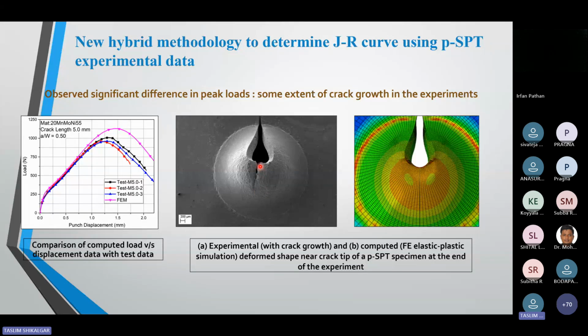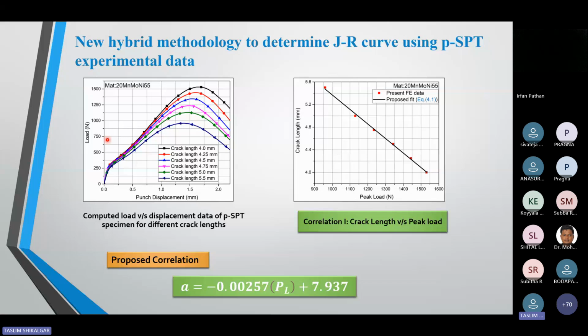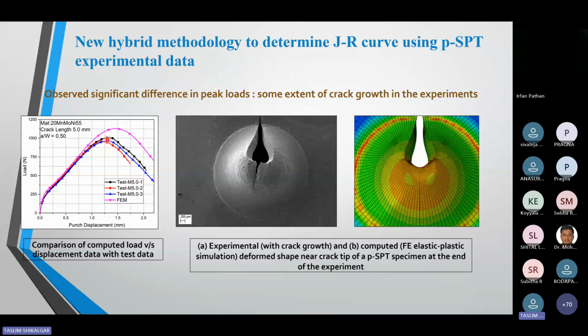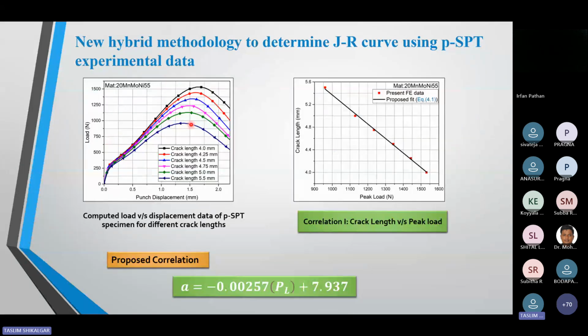So I want to find out the crack growth. How much has the crack grown in this specimen? First I want to find it out numerically and then validate it with the help of scanning electron microscopy techniques. So how can we utilize this picture to get the crack length at this experimental peak load? For that purpose, we decided to go for additional simulations. So we did additional simulations for different crack lengths, and I did these simulations to get the load displacement data. I plotted this load displacement data.